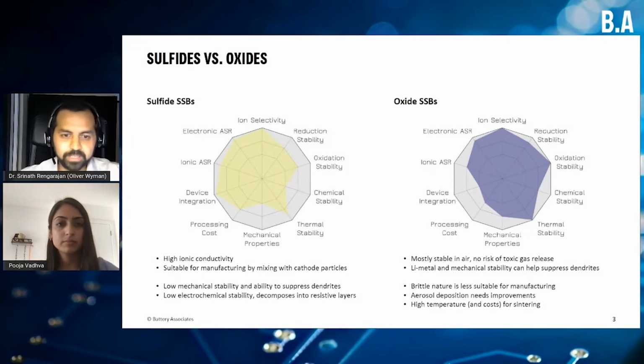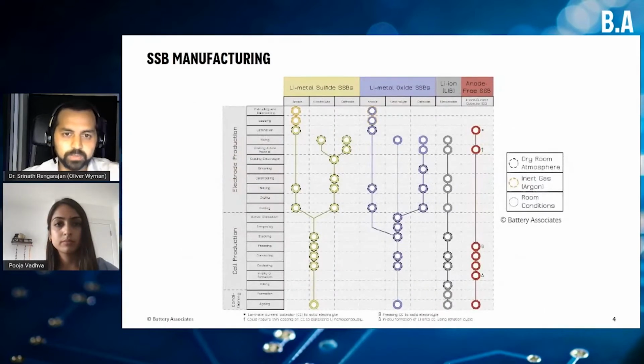Yeah, and I think the main takeaway from that is, of course, that both are technologies which are still under development, and there are a lot of pros and cons for each of them. And this is also reflected when we think about the process steps which are necessary in manufacturing a lithium metal sulfide or lithium metal oxide solid state battery. In some cases, it's not just a dry room requirement, but also an inert gas argon requirement in a glove box, for example, if you're talking about sulfides especially. On the other hand, the promise is that using solid electrolytes gives the potential of doing away with many process steps in between, which has a knock-on effect in terms of reducing costs and improving the profitability of companies selling such products.